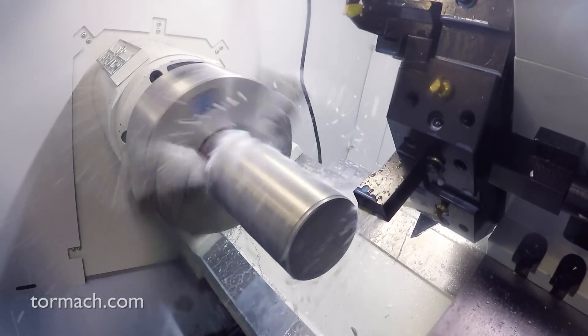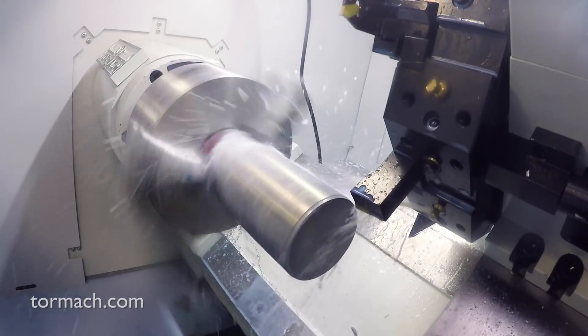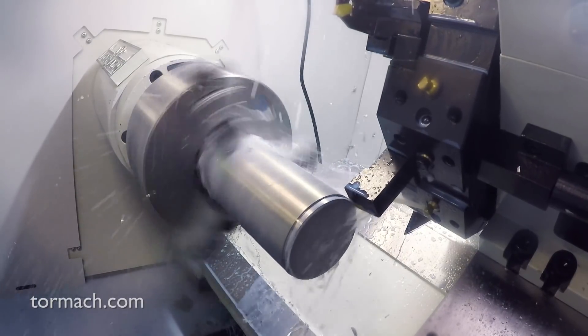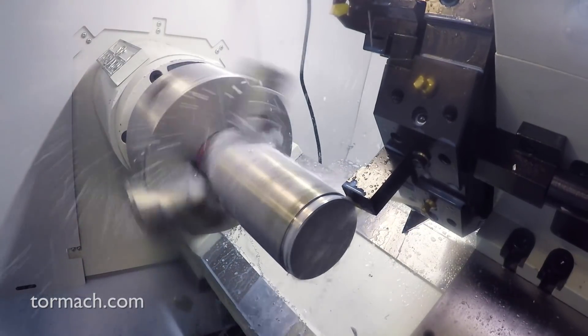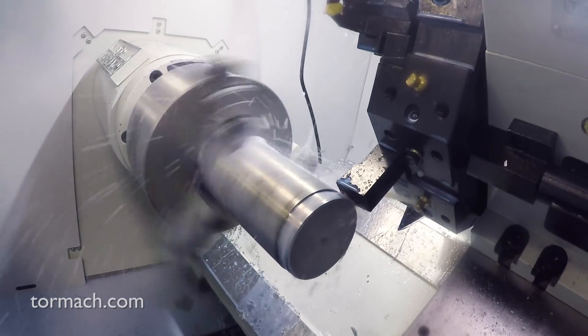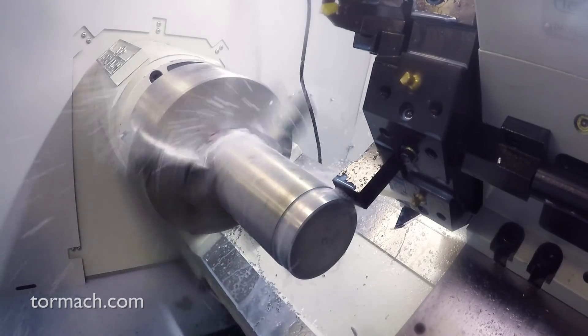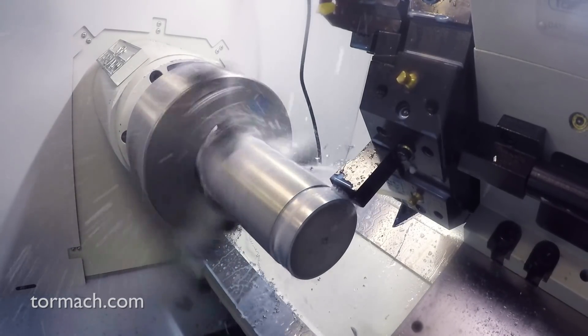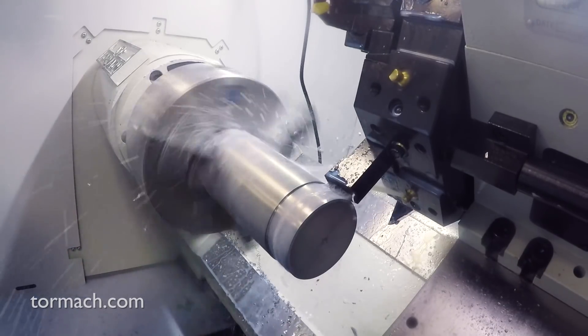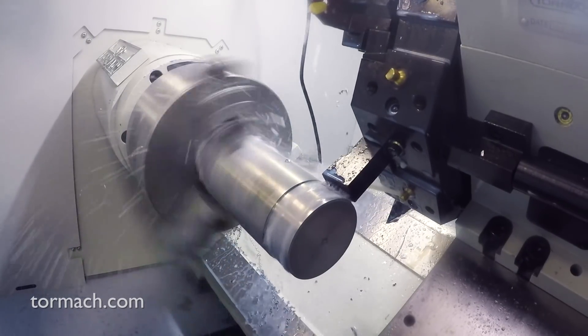Stainless steel is one of those materials that you just need to go for. When you're going to cut it, you need to know your numbers are good and you need to let it cut. As it's cutting, you can hear that it sounds pretty nice. The chips are coming off, they're still silver in color so we're not going too fast. We're forming a nice little curl, the chips look like little sixes.